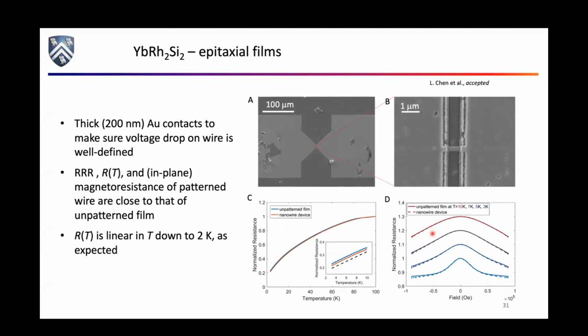And then again, even the magnetoresistance, if I apply a magnetic field in plane, pointing this way, you see that the unpatterned film and the patterned wire have very, very similar magnetoresistances. So this tells you that by making the wire, you have not screwed up. You have not destroyed the material. I can tell you we tried other ways to make the wires, and this doesn't work. So this is the happy way to make wires.